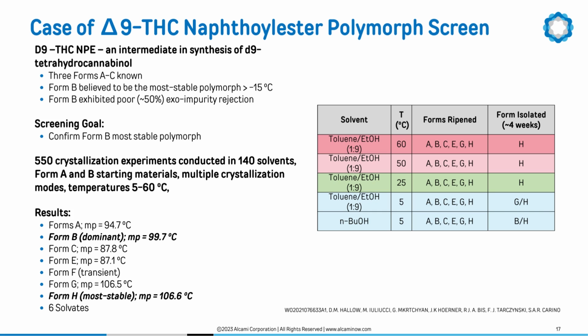So the client approached us with the task of conducting a screen of the ester to confirm that 1. the progressed form B is the most stable, and 2. to assess rejection of the undesired impurity under various crystallization conditions. The comprehensive form screen consisted of 550 experiments and involved 140 unique solvents. In addition, 2 input materials were used, forms A and B, and 5 crystallization modes and temperatures between 5 and 60 degrees C. The screen resulted in the 3 previously known non-solvated crystal forms A, B, and C, a class of 6 structurally similar solvates, a transient form, form F, and 3 new non-solvated forms, forms E, G, and H.